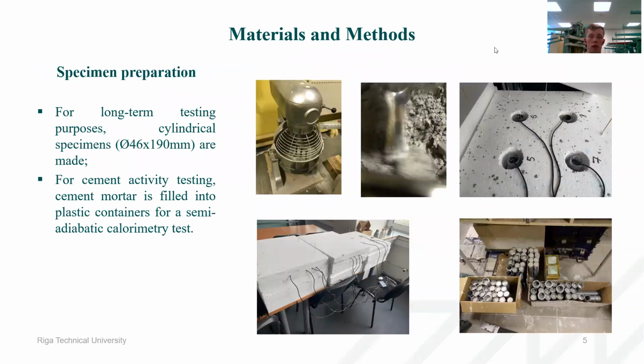After all that, the test specimens were prepared, and for creep and shrinkage measurements, cylindrical specimens were prepared with the diameter of 46mm and height 190mm. And for the activity tests, the prepared compositions were put into specific containers that were then put into polystyrene holders for the measurement taking.